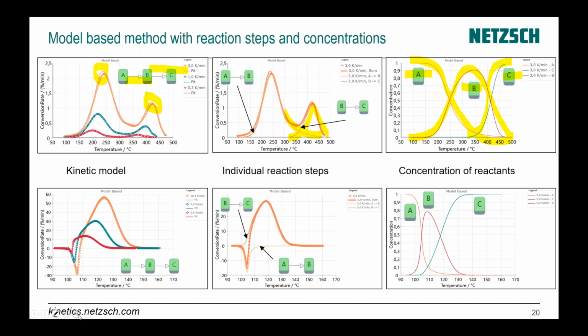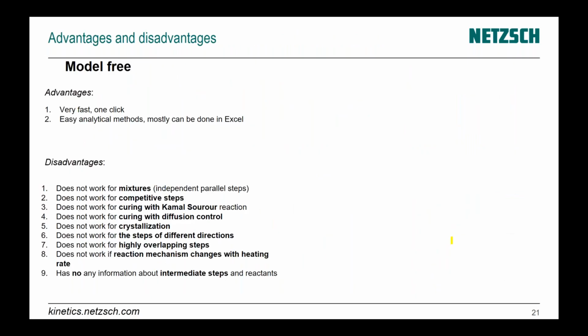It happens really very frequently, and sometimes for TG, you can imagine you have a mixture of two components: one has decomposition with mass loss, and another has at the same temperature oxidation with mass gain. Then you have a process of different directions, and you can analyze them only by the model-based method. In this case, you have step number 1, step number 2, and the final curve is a sum of the steps. Again, there is a possibility to see the concentration of each product, including intermediate products.